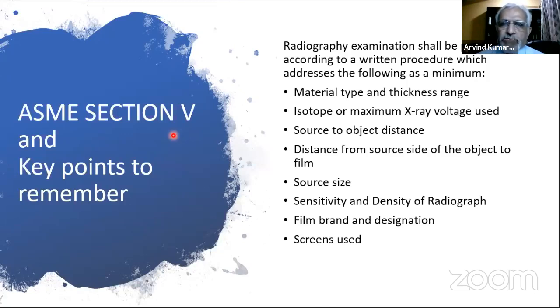Now, an important thing to remember in this is that your examination is to be performed as per a written procedure. This goes without saying for any technique. We'll talk about this in the end also. It requires a written procedure approved by a Level 3, which should be followed for doing any NDT. The previous code for radiography, Section 5, was not giving a mandatory requirement for a procedure for radiography. It was saying that when the density and sensitivity are okay, it assumes that the procedure has been correctly followed. But now in the new revision, they have indicated that for radiography also, the written procedure should be there, which would talk about the minimum material type and thickness range.